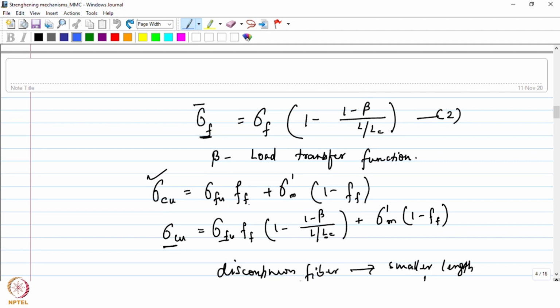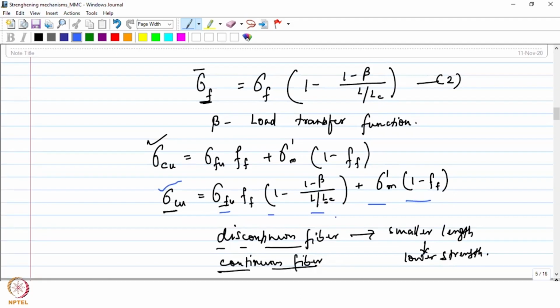Okay, so from that we could also derive the strength of the composite by using this particular equation, and here if we substitute this first term with the average stress on the fibers, then the composite strength will be given by this particular equation over here, which takes into account the L by D ratio as well. Okay, so this tells us that the strength of a composite does not really depend on the volume fraction of the fibers alone, but it also depends on the geometry of the fibers, which is given by the L by D ratio, or the aspect ratio.